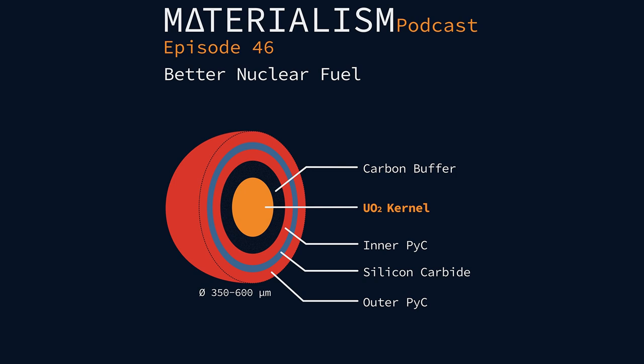Yeah, absolutely. You have to find something that can hold silicon and carbon in a gas phase. So yeah, you're not going to vaporize silicon carbide and have it then deposit. So what they actually end up doing is use this organic silane, specifically methyltrichlorosilane. That's your source of silicon for the silicon carbide? Yeah. And the reaction that proceeds in the deposition process, you go from the methyltrichlorosilane to silicon carbide and hydrochloric acid gas.